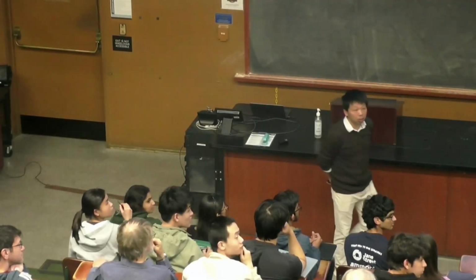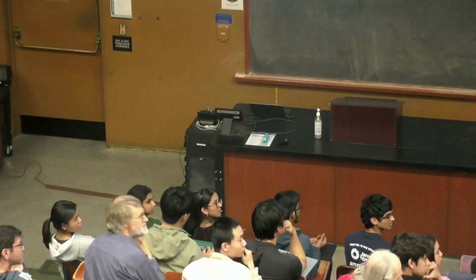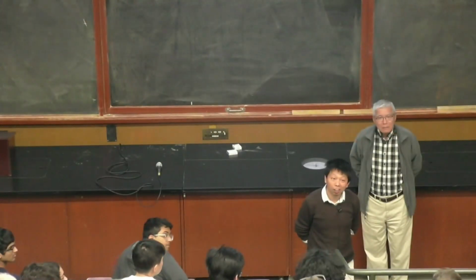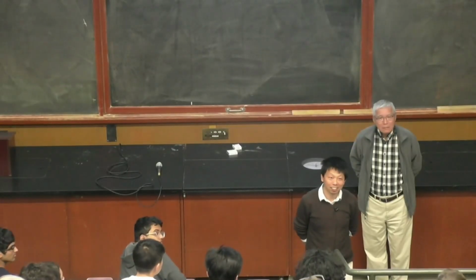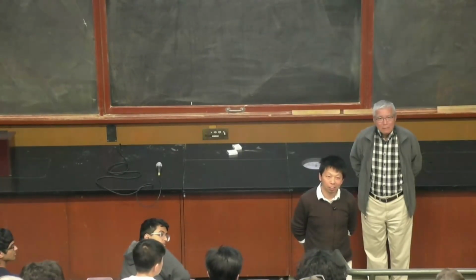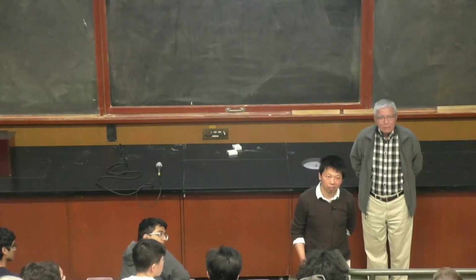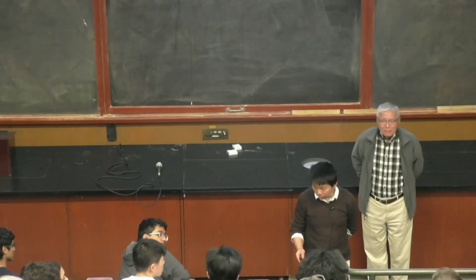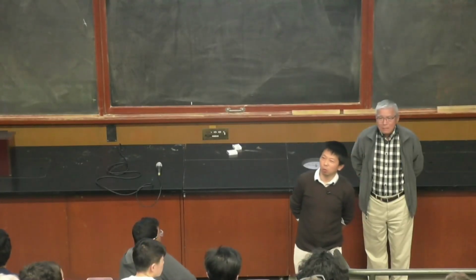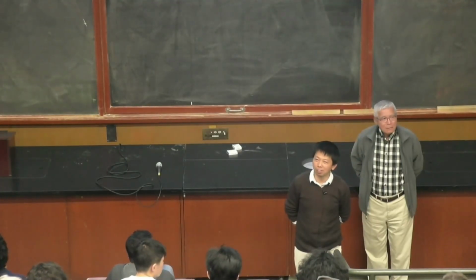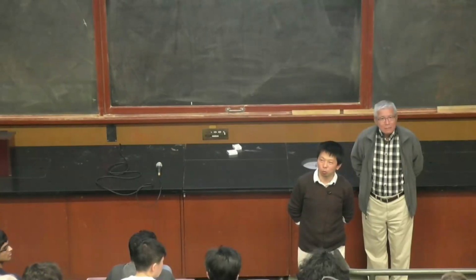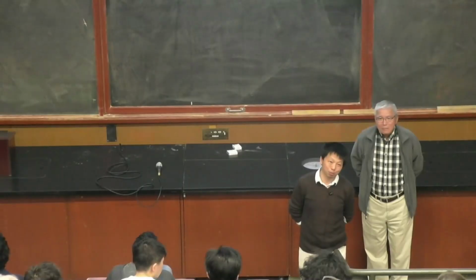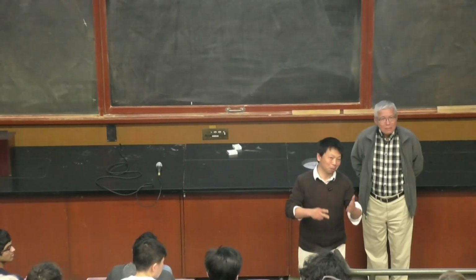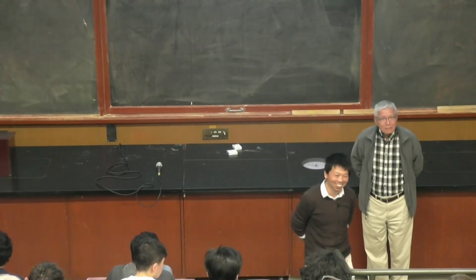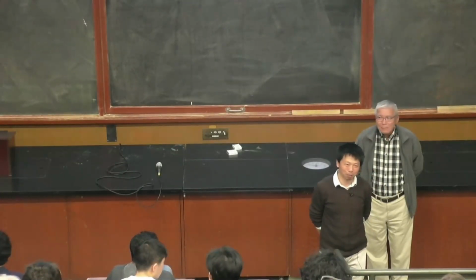Yes. Everything you mentioned is about the electronic degrees of freedom, but of course there is a lattice there also. I wondered to what extent electron-phonon coupling might explain the renormalization of the exchange interaction or other effective interactions. We think the electron-phonon interaction is relatively weak at this low energy level. But it's not obvious how the phonon plays a role. So it's possible, we should check. But it's not obvious why it would be important here.